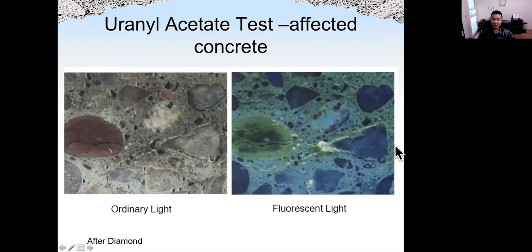Okay. As we can see from here, after the procedure, under normal light we don't see anything actually, but under fluorescent UV light we see the gel inside these cracks. The whitish color is the gel. So from there, we can identify the cracking is caused by ASR.